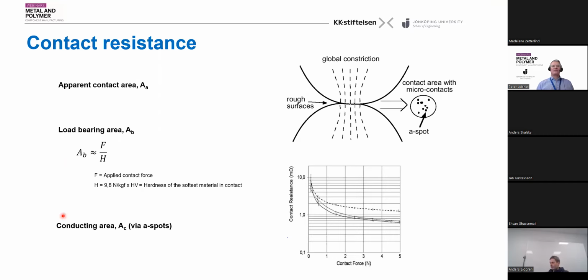And the same thing will also affect these A spots, the conducting area. This is illustrated to the right, where we have the contact resistance on a logarithmic scale as a function of the contact force. Here we can see for 3 different materials that it drops when you increase the force. And it drops a lot actually in the beginning, because it's a logarithmic scale.